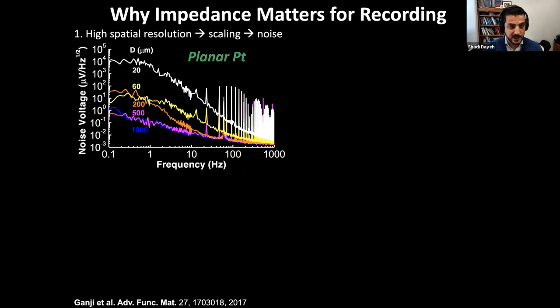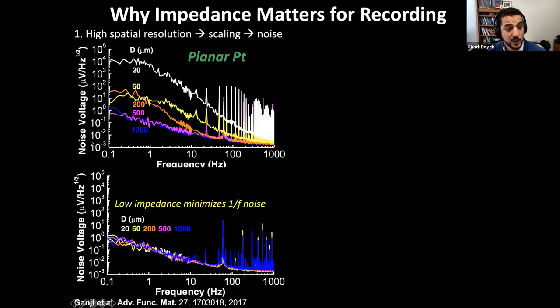So why does impedance really matter? I said earlier that when we scale the metal contacts to small sizes, their impedance rises, and that compromises the recording quality. This plot right here basically illustrates the problem. First let me say what we're looking at. We're looking at the noise voltage as a function of frequency for different diameters. This is the diameter of the metal contact that's open to the electrochemical interface. As the diameter decreases, we see that the noise voltage rises typically as a function of 1/d². And when we go to 20 microns, we have about 6 orders of magnitude higher noise at low frequencies.